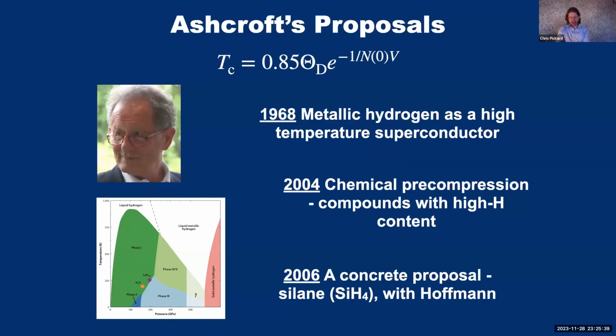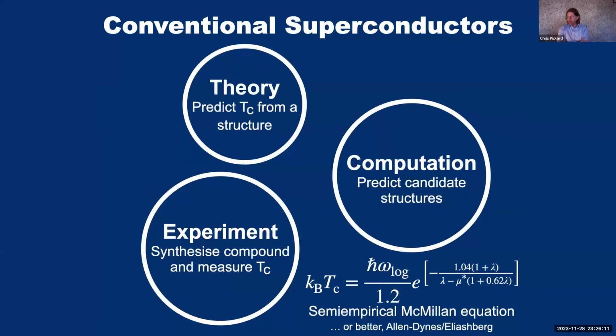And very rapidly, using this random structure searching, we found much more stable structures than those that they had suggested. And at the pressures where they felt they had superconductors, we found that a band gap actually opened up. It was not a metal and therefore couldn't be a superconductor. But at higher pressure still, the material did appear to become metallic. So we left open the possibility that maybe silane at high enough pressure might become a superconductor. So that was the start of our foray into that field. And the basic reason we're able to do these, even think about designing superconductors from first principles now, is because of the existence of a set of experimental and, in particular, theoretical and computational techniques for conventional superconductivity.